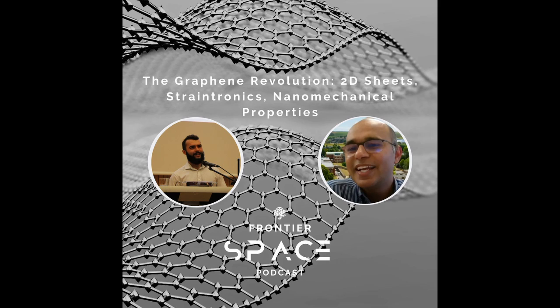These are disorders. So you cannot improve the electrical properties, but you change the electrical properties. Sometimes change is required rather than improvement. I can give you an example. Graphene itself, if it has no defect, is useless for switchable devices. You cannot switch it. You need a semiconductor. That's why copper is not used in the semiconductor industries, and we need a kind of band gap to use it as a switch, like on off, 1 0. Otherwise it will remain on, like it will always be 1, or it will always be 0. You need a 1 0 1 0 kind of arrangement. So switching is required. When you switch it off, it should flip down. It should give another signal. That is missing in the graphene.